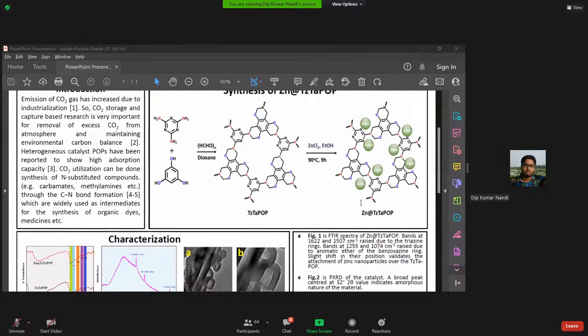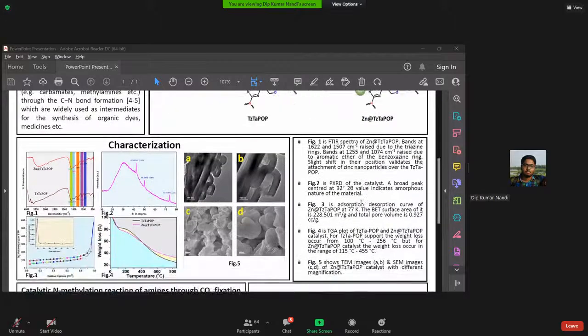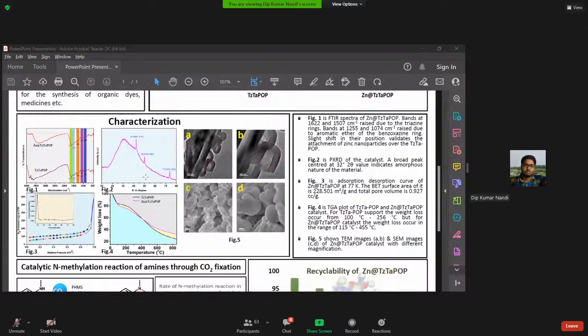You can see the structure here, and I have done the characterization. You can see the IR spectrum. The IR spectrum was done using two different methods. First, we did it without the metal, and second, with the metal, zinc. And here is the XRD data, and we saw the TGA analysis. From the thermogravimetric analysis, we see that it is stable at various temperatures. So we can do various reactions over a wide range of temperature.